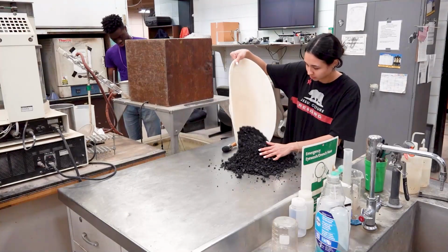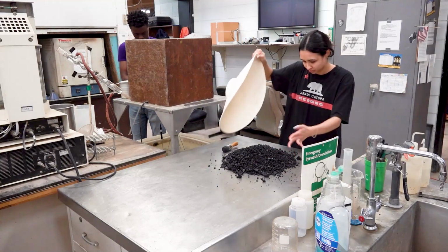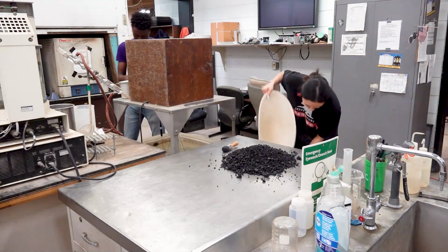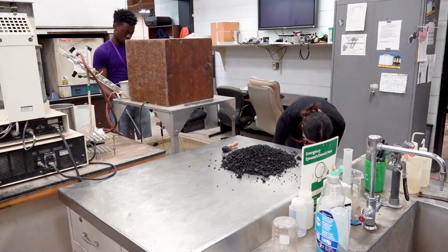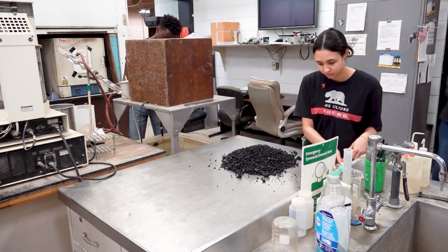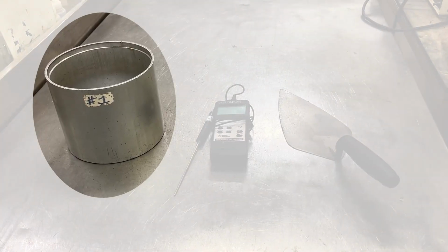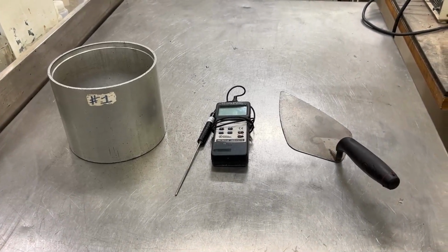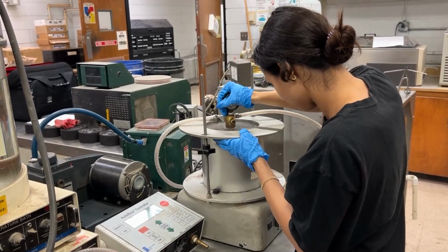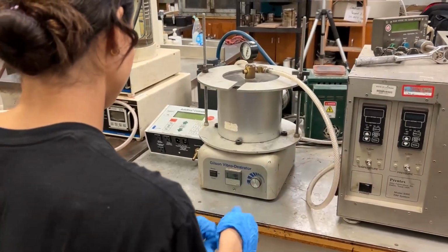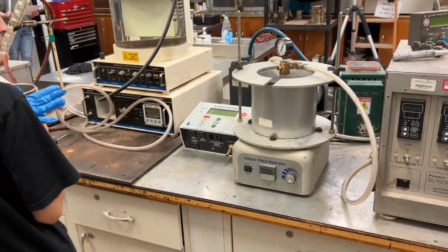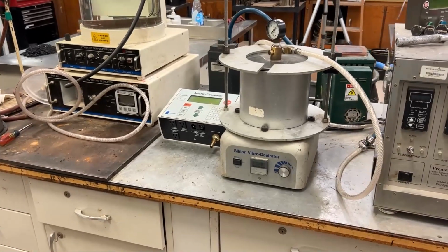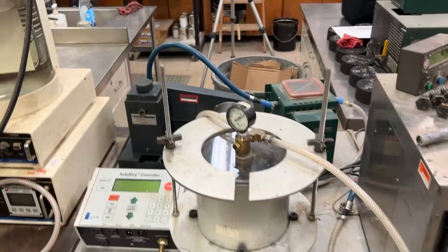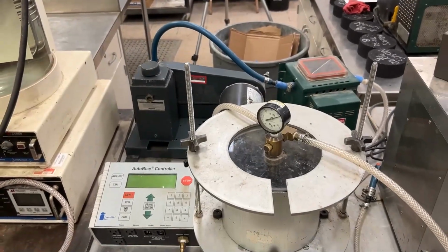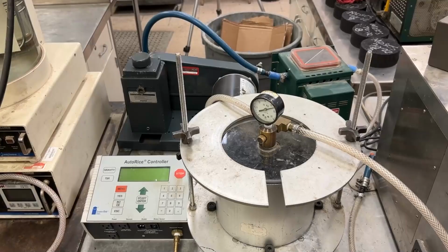Listed below are materials needed to perform this test. A 6,000 gram sample of asphalt material in accordance with DOTD S203 from the Material Sampling Manual. A glass, metal, or plastic pyknometer with a volume defined utilizing a glass capillary stopper, capillary lid, or glass plate. A vibrating table or shaker to perform consistent, automatic agitation of the vacuum pyknometer, and a bleeder valve attached to the vacuum train to facilitate adjustments of the vacuum being applied to the pyknometer.